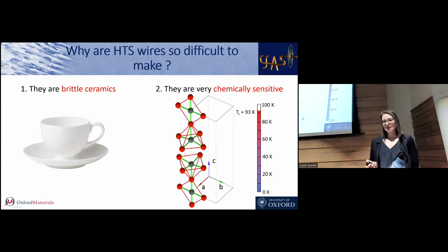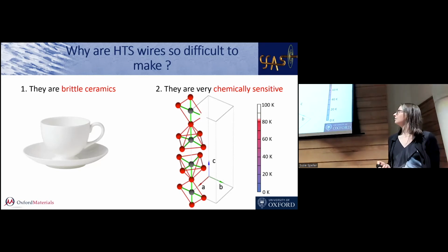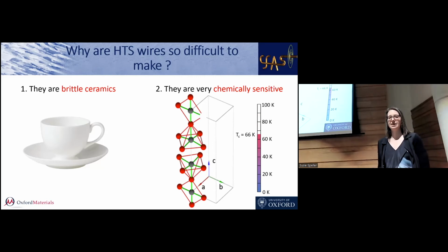The other problem is that all those atoms that we've got have got to be in the right place. We've got to have the right amount of them in the right place. And oxygen is a particularly mobile atom, and it comes in and out of the structure really easily. If we just take one of the oxygens out, say from that place, the critical temperature comes down by several tens of Kelvin, maybe to about 60 Kelvin.